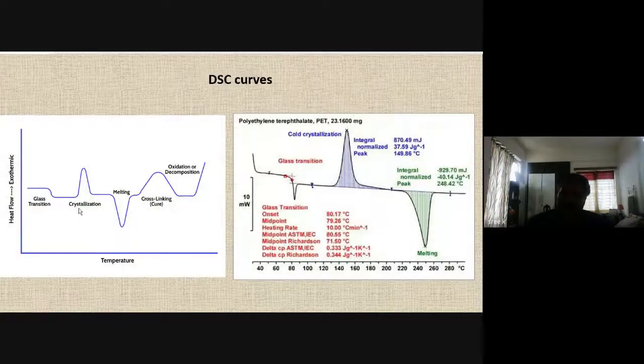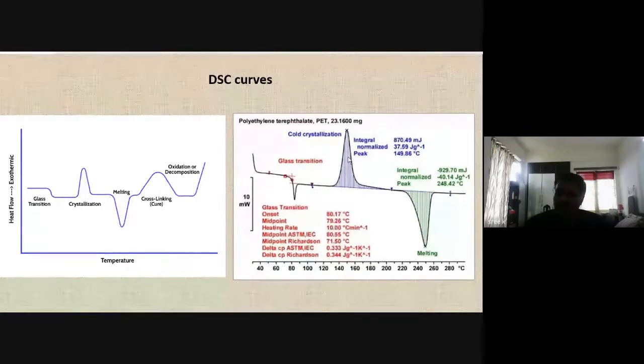So what you get is a plot of heat flow versus temperature. This is a crystallization peak, an exothermic peak, and you take the area of the peak to get the enthalpy of crystallization. Knowing how much material you used, you can get the heat flow from the graph, and the temperature at which crystallization takes place - the onset, and other details like melting.